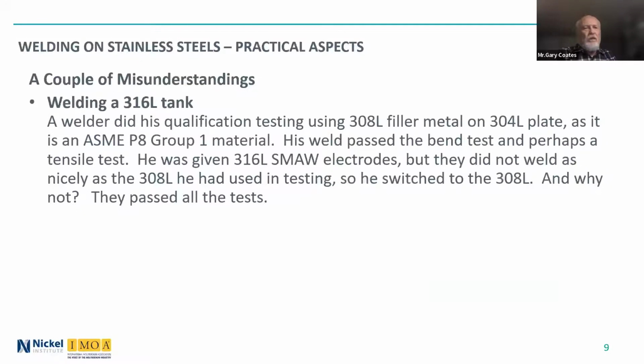So another example on a 316L tank, a welder did the qualification testing using 308L filler metal on 304L plate. That qualified him for welding the ASME P8 Group 1 material. His weld passed the bend test, and maybe a tensile test was done too. And then he was given the 316L shielded metal arc electrodes to weld up the tank, but they didn't weld as nicely as the 308L he had used in testing. So he switched to 308L. And why not? They passed all of the tests that he had to do.